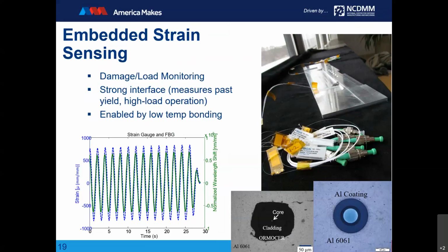So many fiber optic cables on the market have a plastic coating on them. This plastic coating does deform quite a bit, but we saw similar performance in that by compressing that plastic, by flowing metal around it, we were able to transfer that strain again from the matrix to the fiber successfully.